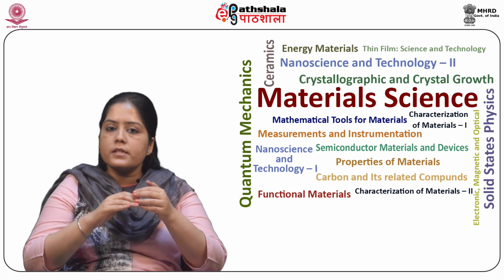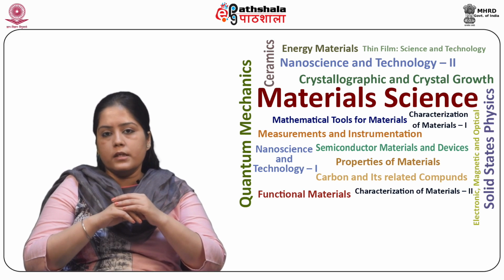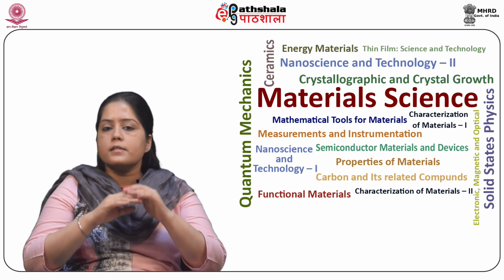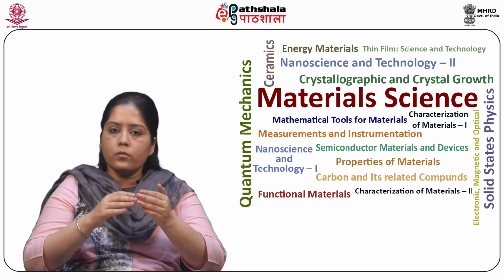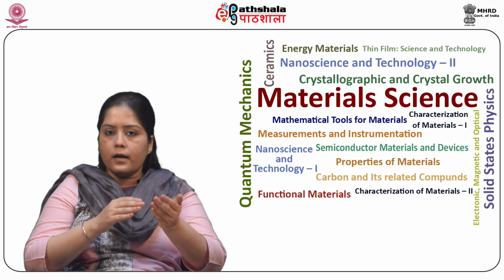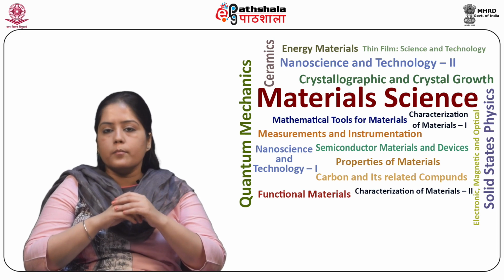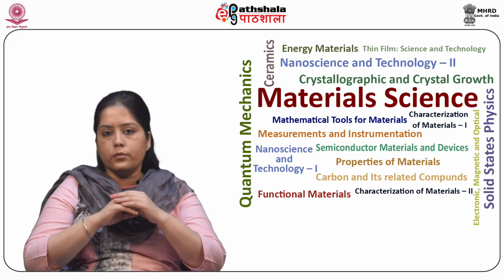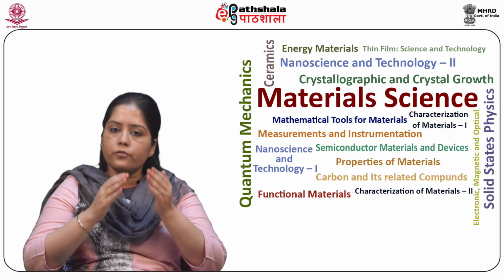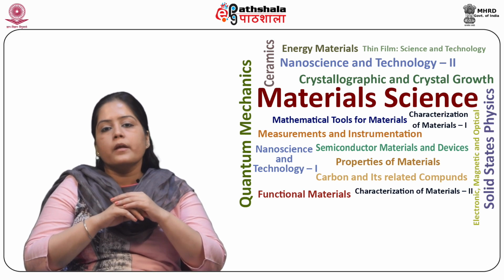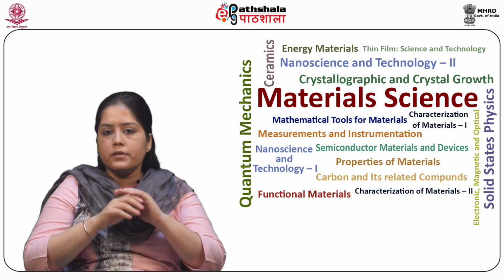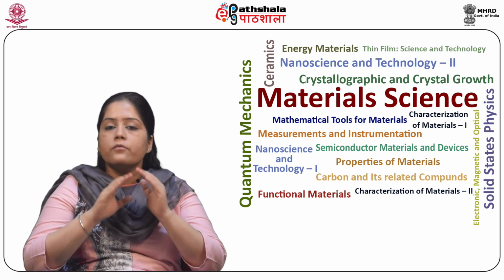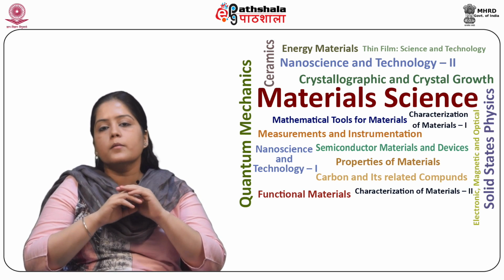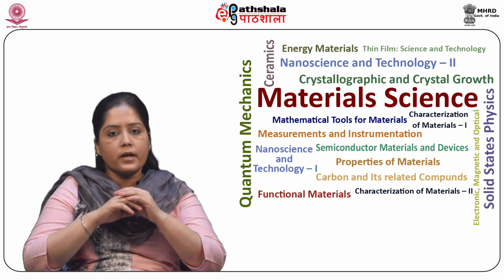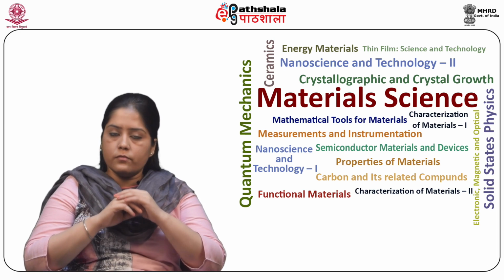So the intrinsic electrical conductivity is given by sigma_i equal to q ni multiplied by (mu_e plus mu_h). So for the case of silicon at room temperature, the intrinsic conductivity is equal to 4.3 multiplied by 10 to the power minus 6 ohm centimeter inverse.